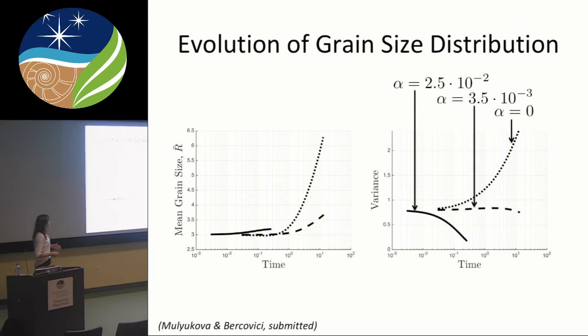All right, so this can quickly be demonstrated. This is back to what I get reported and what we can compare these theoretical models with: evolution of mean grain size through time and evolution of variance through time. Both of these parameters tell me what are the physics that are governing my grain size evolution. Alpha being 0, this is this dotted line, so I'm just having increase in mean grain size and increase in variance, meaning it's broadening.